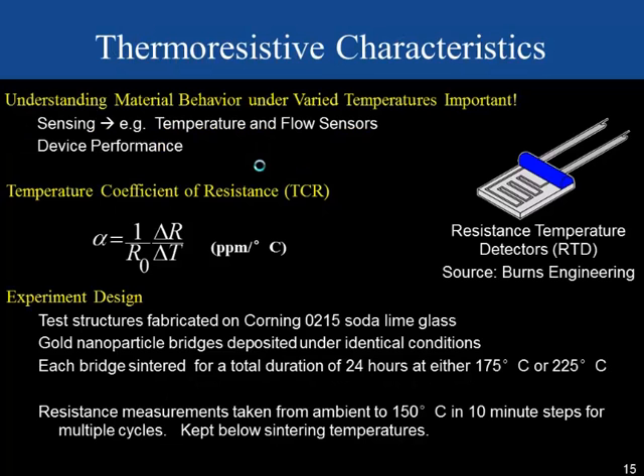Now, after we started this work, one thing we wanted to understand was the temperature response of these films for a couple of reasons. One, understanding the temperature response of these films is important for device design, as sensors and other devices often undergo a variety of ambient conditions. Also, the unique properties of these films may be useful for things such as platinum, or not platinum, in this case gold, RTDs, and flow sensors. An important measure of temperature is the temperature coefficient of resistance, which is shown with this relation here. And that's what we chose to measure using our technique.